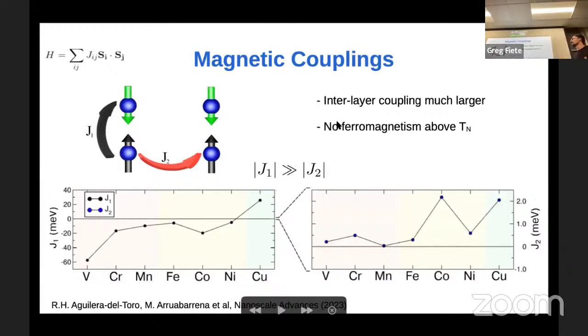These configurations can again be modeled with a simple Heisenberg Hamiltonian of one interlayer and one intralayer coupling. And well, I got both of them here. The main takeaway here is that now, in this two-dimensional case, the J1 interlayer coupling is much larger than the intralayer coupling. You see the order of magnitude here, from -60 to 40 meV, and here you have just 1 to 2. We see that these atoms are way more coupled magnetically in the vertical direction, let's say, than they are inside the plane. So we will no longer have this case in which we can have ferromagnetic planes at larger temperatures than the Néel temperature.